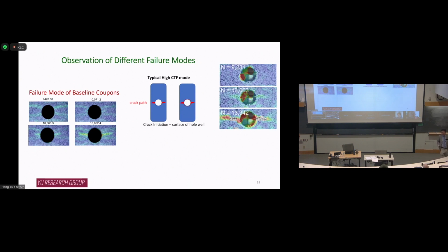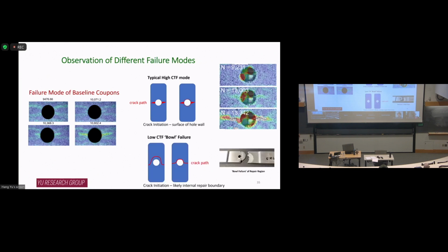So we can actually get a comparable or even better fatigue performance than the base material, because we changed not just the repair geometry, but also the microstructure of the deposit material. I don't have time to go into detail, but it does relate to the crack initiation mechanism and the crack propagation mechanism. If you don't do a good repair, you're going to fail at the repair region. But I think what we can say is we have developed a recipe. We can get good repair performance.